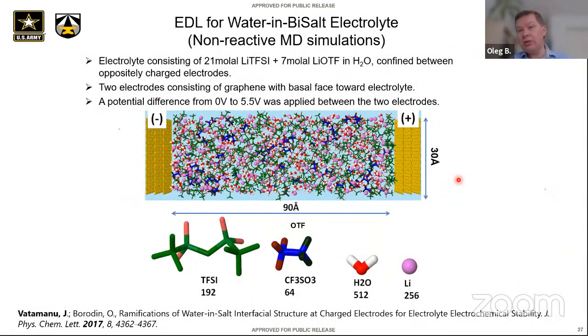So now, once I introduce this 21 molar water-in-salt, we want to show MD simulations for the water-in-salt. Specifically, I'm going to take 21 molar. That's the solubility limit for lithium TFSI. However, what the Johnson group has shown is that 7 molar of lithium triflate, shown here, can be added to the TFSI with water, and that has slightly improved the stability further. So the question is, what happens at the double layer in the system?